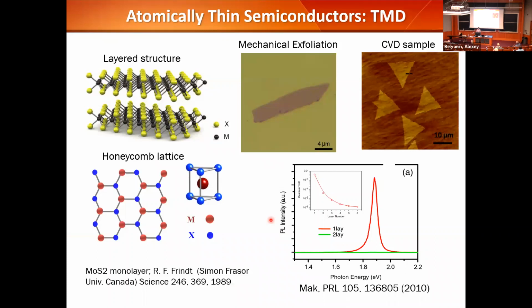Okay, so this is the material I'll be talking about for the rest of my talk. Transition metal dichalcogenide: there are 3 layers of atoms in a single unit cell. Transition metal in the middle, and then chalcogenide atoms on both sides. Now, if you look at these materials from top down, you have a honeycomb lattice. In graphene, you also have what's called an AB lattice, but you have the same atom occupying the AB lattice, that's carbon. This material is just slightly more complicated. You have different atoms on the AB lattice.